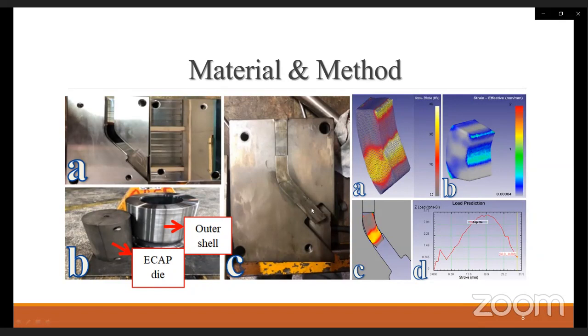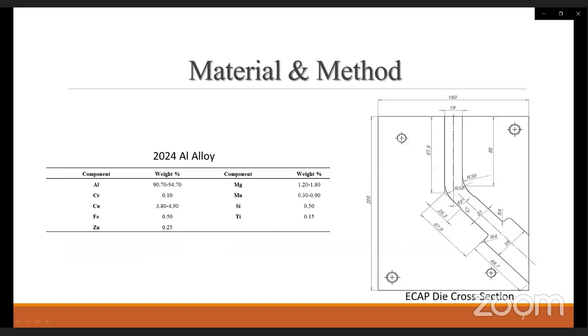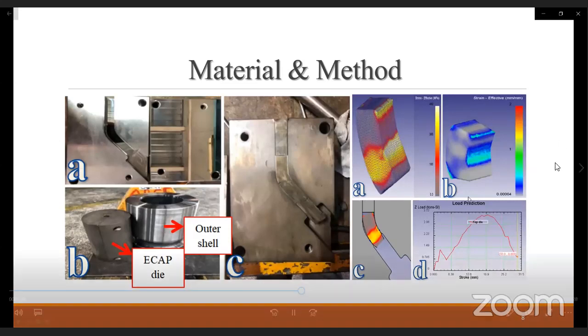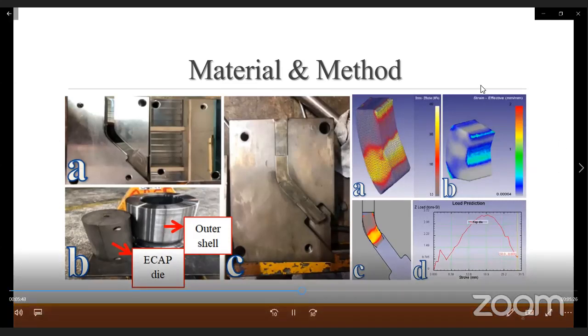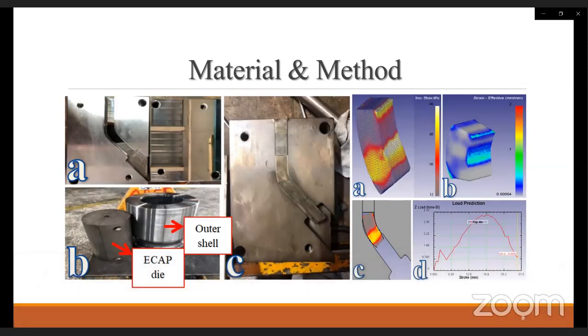And in order to solve this problem, the channel is expanded 1 millimeter after the curvature of the turn is completed. As you can see on this simulation figure, also on this technical drawing, the channel is expanded a little bit. And then the sticking of the samples inside the ECAP die is solved. Finally, the ECAP die works smoothly. 1 pass, 2 passes, 3 passes, and 4 passes have been made with the ECAP die.